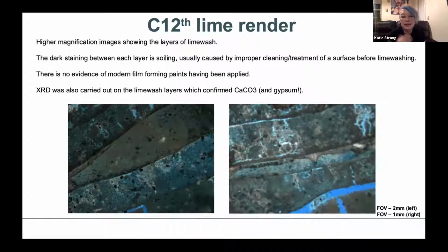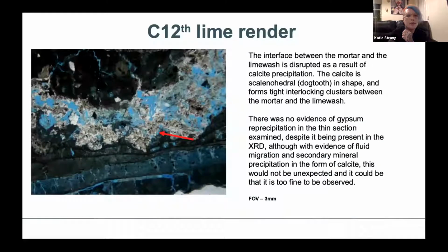But as I said, we did do XRD, and the other thing that we noticed is that there's quite a lot of gypsum in your lime wash as well, which is quite unusual. So this is an image to look at the area above. This is the interface between your lime wash here and the rest of your binder. And in this area, it's just absolutely full of calcite. So this is reprecipitation of calcite.